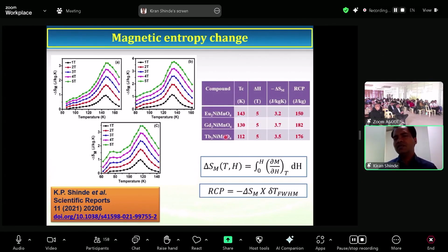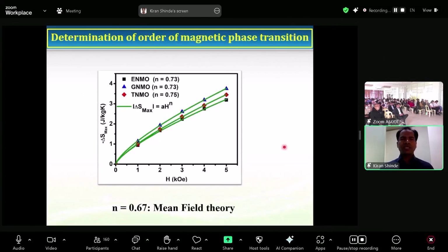Similarly, when we study the B site element like nickel, if we replace the nickel with a different transition metal, we can get a change in the Curie temperature. So we have to tune the Curie temperature according to our application purpose. This slide again shows delta SM with respect to the external magnetic field. We use the 0 to 5 Tesla magnetic field, and when we fit this data using this equation, we get this N value for 3 different compounds, 0.73, 0.73 and 0.75, which is nearly equal to the mean field theory value of N, 0.67. This confirms that our studied compound shows a second order phase transition.